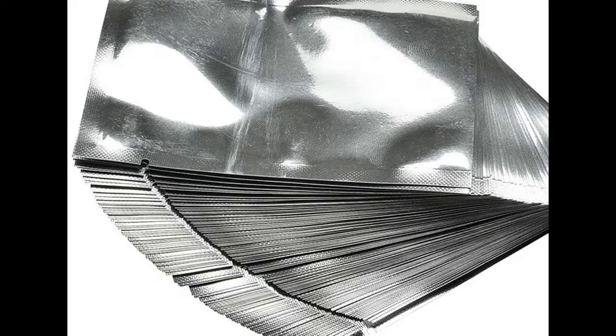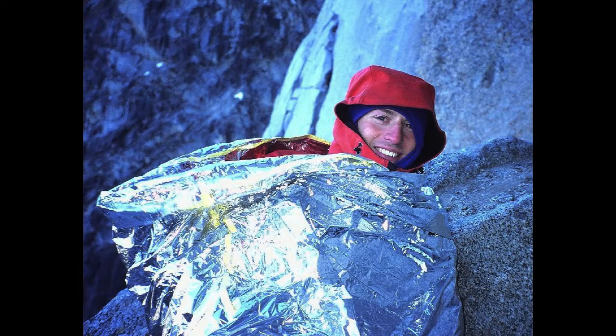The aluminized mylar additionally has high tensile strength, low density, and the ability to be heat sealed, all of which make the material ideal for use in thermal insulation. Due to its high reflectivity, the aluminized mylar can reflect up to 99% of light and reflect up to 90% of body heat back. In spacesuit designs, 4 to 5 layers of aluminized mylar are necessary in order to increase the effectiveness of the thermal insulation. Aluminized mylar's low density makes it a lightweight material, which allows for multiple layers to be used in suits.